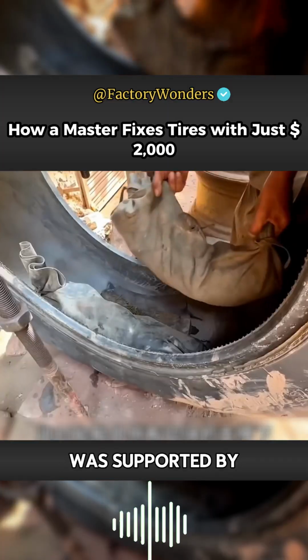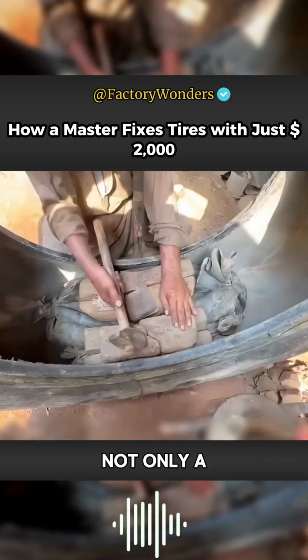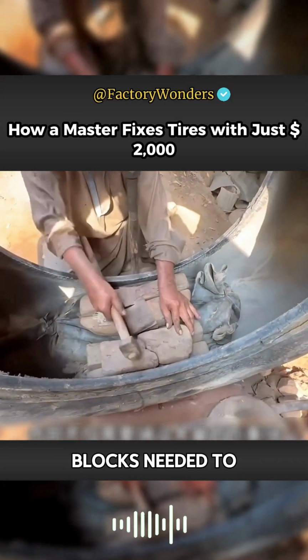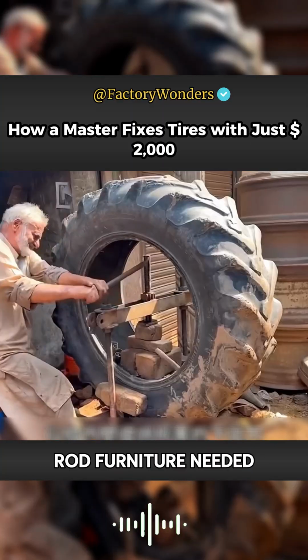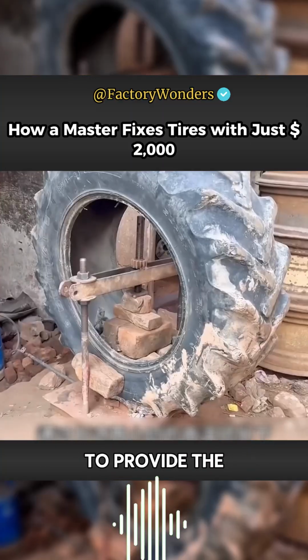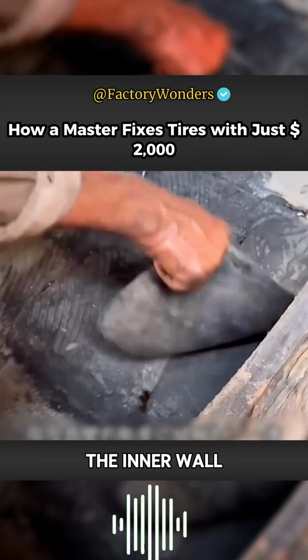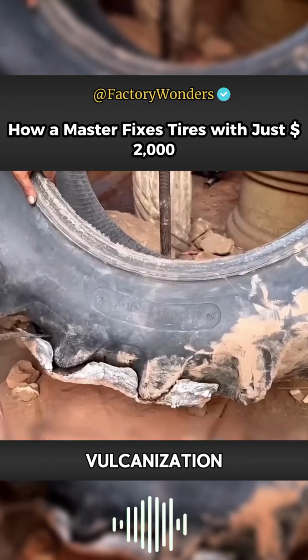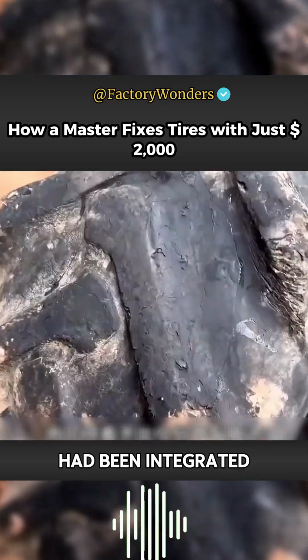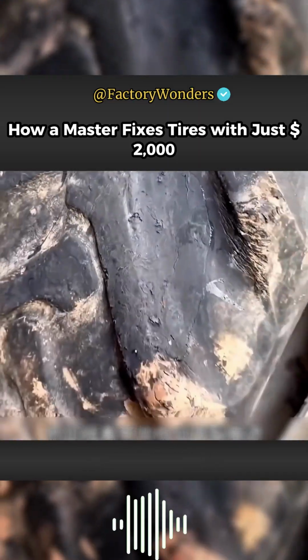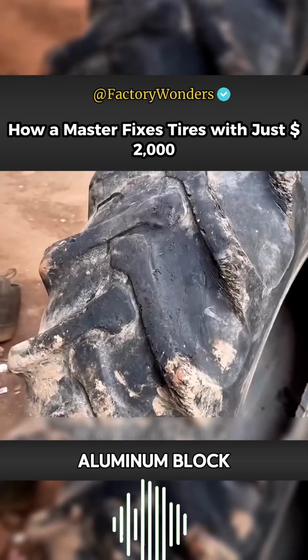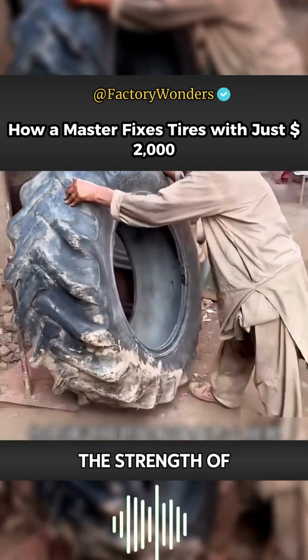When the tire was supported by the aluminum block on the outside, not only a large number of weight blocks needed to be laid inside, but also a steel rod fixture needed to be installed to provide the required downforce to the inner wall. After 2 hours of high temperature vulcanization, the tire skin of the wall had been integrated and there was no sign of cracking on the outside of the wound supported by the aluminum block. So what do you think of the strength of such a tire?